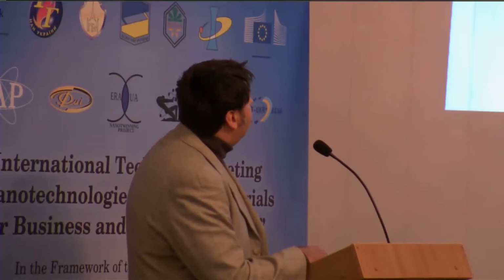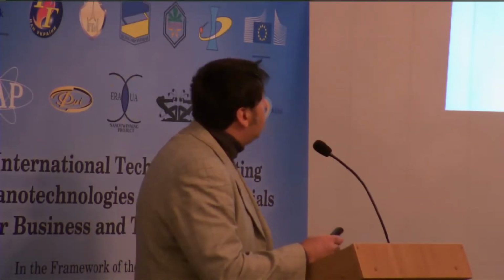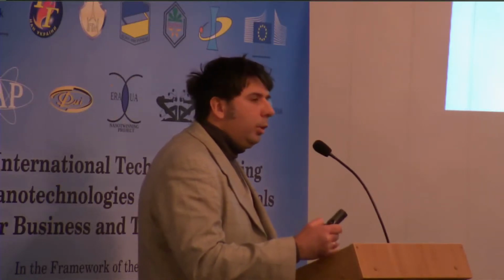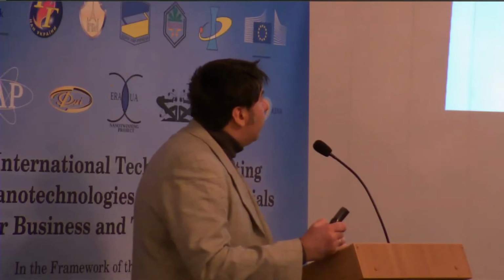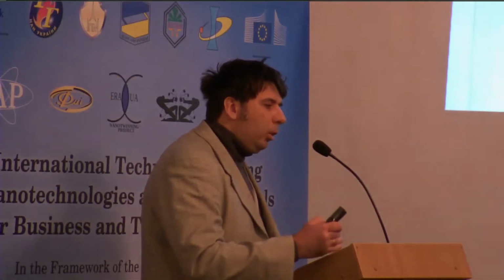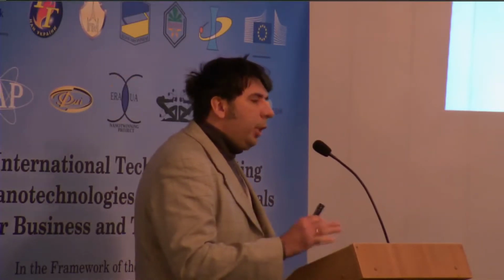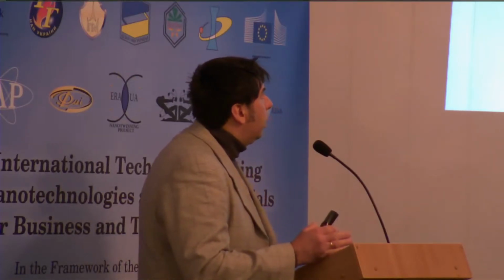It has to be mentioned that we tested two technologies. The first one is spark plasma sintering technology. It could be adapted for industry very quickly, and this technology is not very sensitive to nanopowder quality. Because a pressure and high heating rate are applied, we can obtain fully dense nanocomposites very quickly, and we can change suppliers of nanopowders. But the equipment for spark plasma sintering is a little bit higher in price.